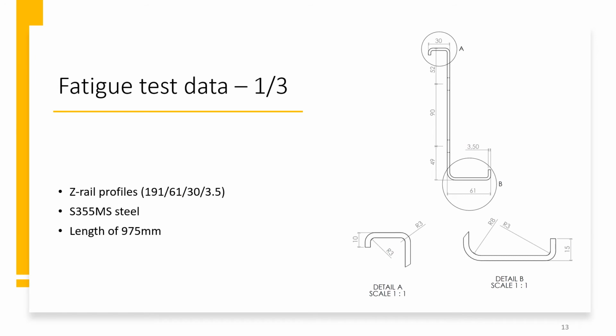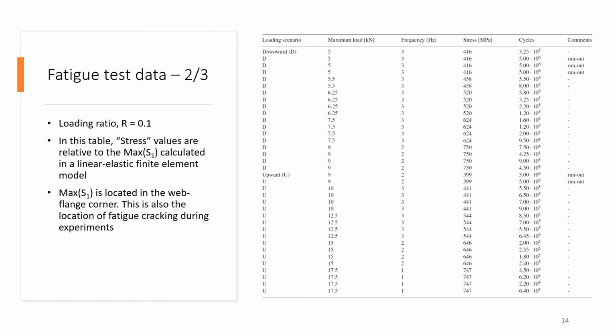So now I will share with you some of our fatigue test data obtained by the testing of this specific rail. We have the geometry of the rail section with the dimensions, and the rail is composed of S355 MS steel and has a length of 975 millimeters. Our fatigue tests have a loading ratio of R equals 0.1, so 10% of the maximum load.